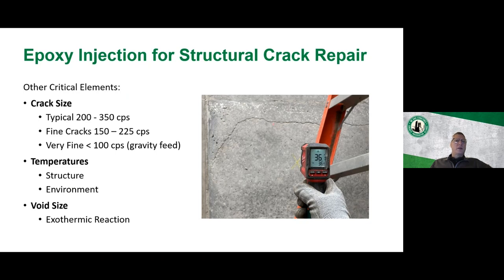Important elements for it, when we're talking about epoxies, you have many different types of viscosities. And so you can go very fine to thicker. Many people think, okay, let's go with the lowest viscosity possible. But if you end up doing that and you start trying to repair your cracks, that ultra low viscosity can start coming out the pores of the concrete. It can go into areas that are unintended. So make sure you right size your viscosity to the repair that you're trying to accomplish.